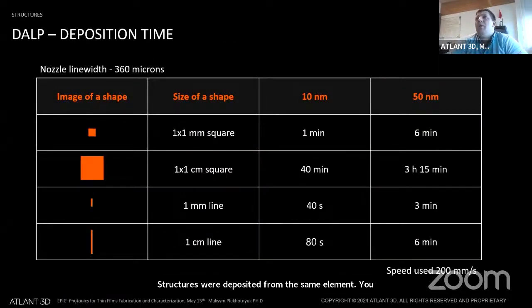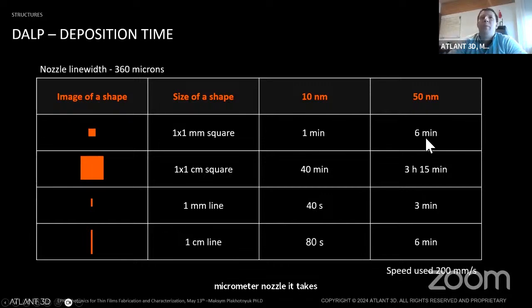You might ask, well, how much time it takes to process? Depends, of course, on the micro nozzle, but 1 millimeter square, for example, if it's used with a 360 micrometer nozzle, it takes like 1 minute to deposit 10 nanometers, and 6 minutes for 50 nanometers. And the nozzle can be made for 1 centimeter, also 1 centimeter wide. So it also would take 1 minute, but for 360 micrometers, it's like 40 minutes.